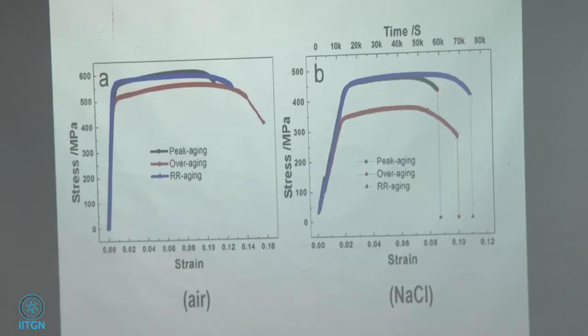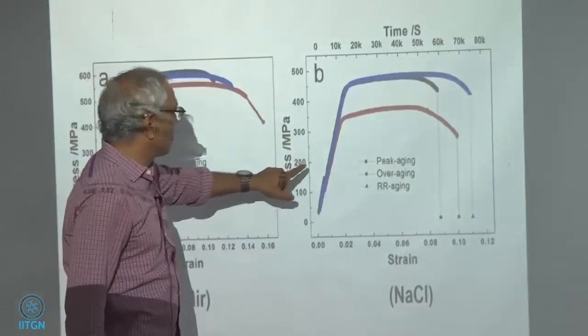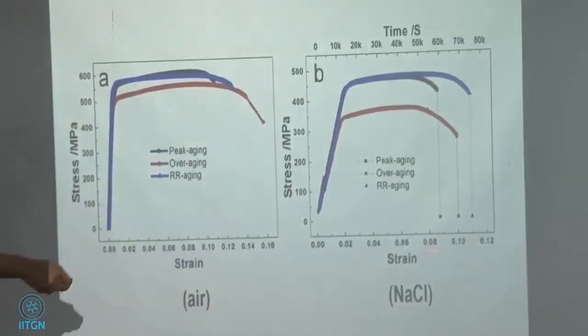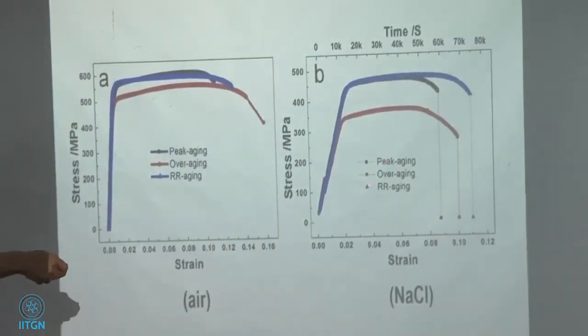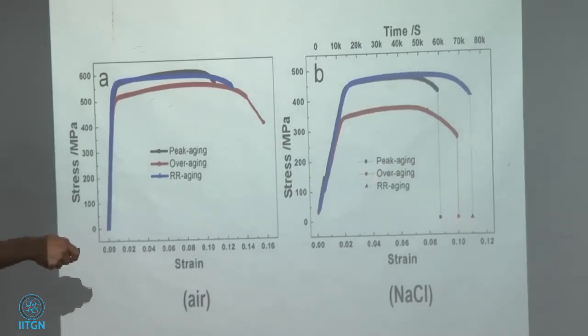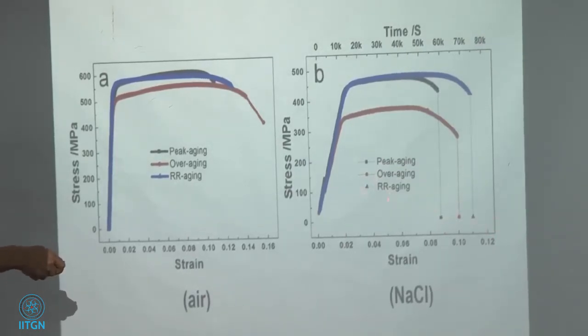Okay, let's look at the strain in sodium chloride. That's a better indication because that's corrosion. This is corrosion, right? Sodium chloride solution. The peak aged is failing at this strain, right? The overaging is failing at this strain. But look at retrogression reaging. Wow, there.